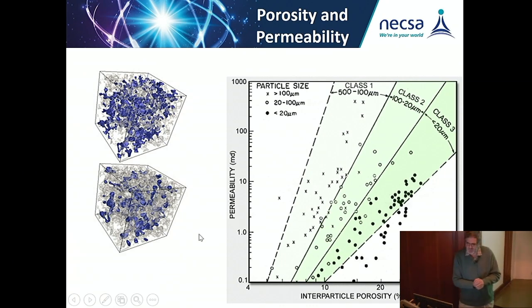So when you look at porosity, you can also determine the permeability of that mineral. The ultimate is with a certain particle size. When you determine your porosity, you can create this kind of a graph where your porosity is interlinked with the permeability within your sample.